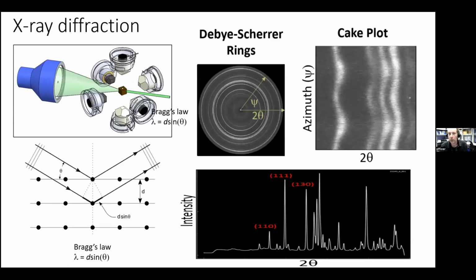We can also, with X-ray diffraction, measure the pressure and the deviatoric stress that we get. Basically, we're collecting full diffraction rings. Under hydrostatic conditions, these rings will just be circles, but as you generate some deviatoric stress, they will start to become ellipses.